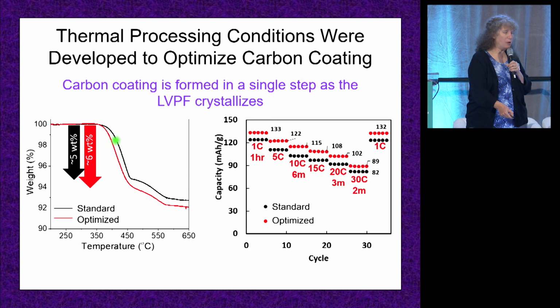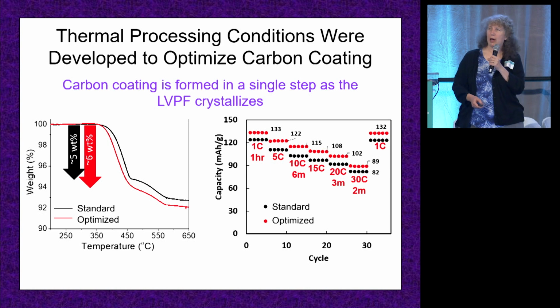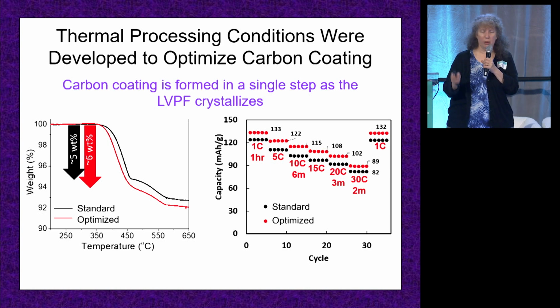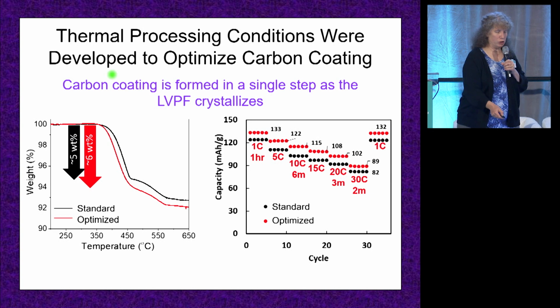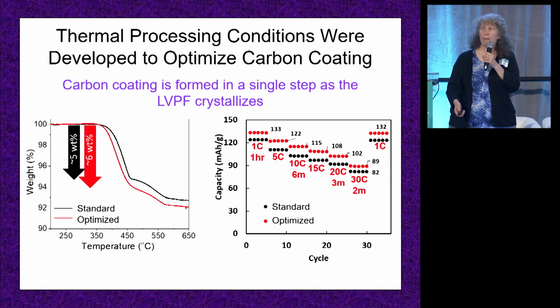To optimize the amount of carbon. This is a method where we just burn off the carbon, so the bigger the drop, the more carbon we had initially. And what we find is when we put more carbon to make the material more conductive, it charges faster. So the red has more carbon than the black. We keep more capacity at higher rates.